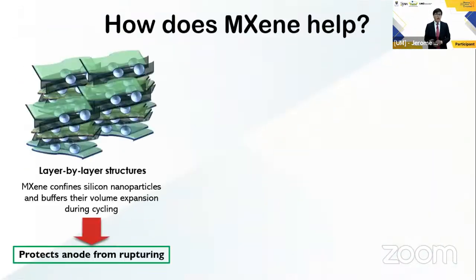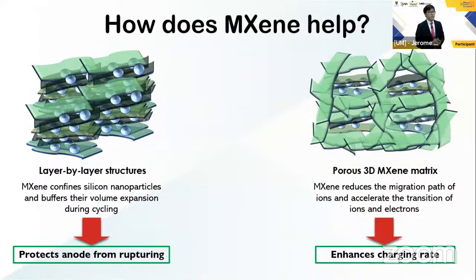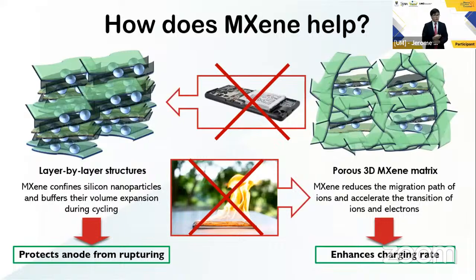The former structure confines silicon nanoparticles from overexpanding and buffers their volume expansion, protecting the anodes from rupturing, whereas the latter can reduce the migration path of lithium ions and facilitate the movement of ions in and out of the electrode, resulting in an improved charging rate. In real life, your battery will no longer get swollen after a few years of usage, and it won't get hot after a fast charging session.